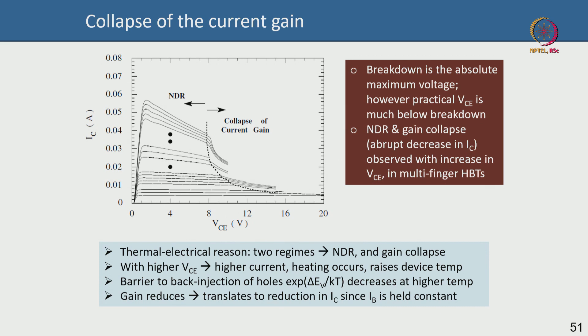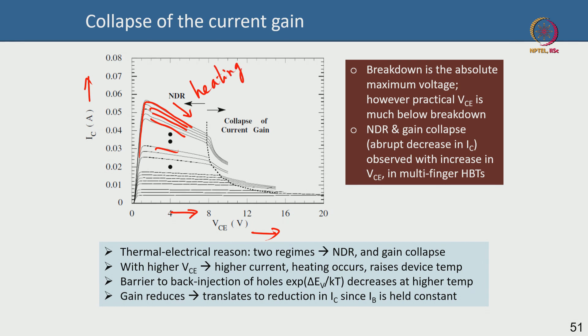The next important concept is the collapse of the current gain. Plotting the collector current versus output voltage in a common-emitter configuration, we see a typical output characteristic — except the current is not saturating; it is coming down. This is called NDR, negative differential resistance: with increasing output voltage, your current is actually decreasing. The rate of change of current with voltage is negative. This is primarily a manifestation of heating, although in compound semiconductors like GaN HEMTs it could also be due to traps.